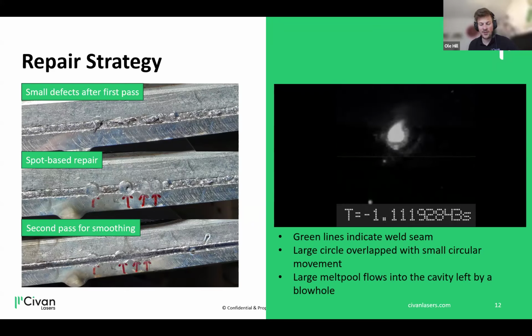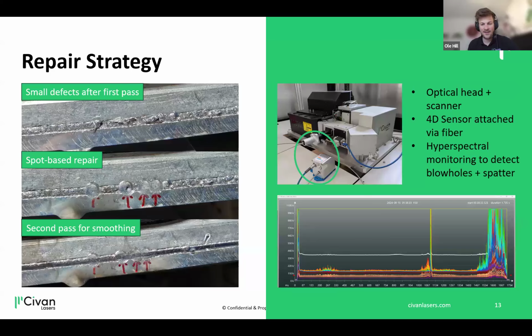Well, this is a good question I hear coming from your mind: how do you know where to repair? Where's the blowhole? We incorporated a sensor for that. It collects data from the focal spot. It is basically collecting all the radiation happening during the laser process, and you detect the peak caused by a blowhole. You take the timing from the start of the process until this event occurred, and because you know the trajectory that you welded with your scanner, you also know the position of this error. So in that way, you take the data, analyze it automatically, go to the desired spot and apply your spot repair.